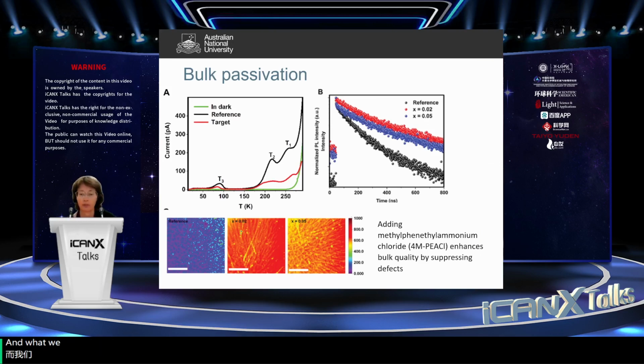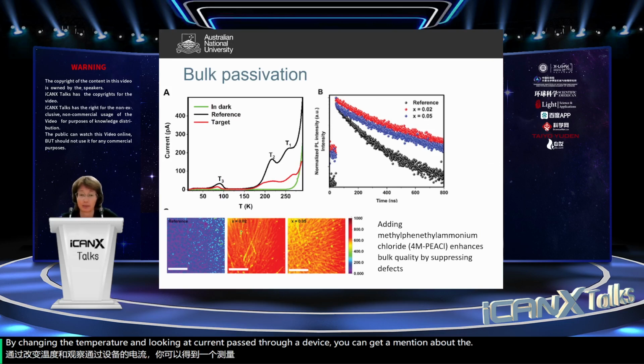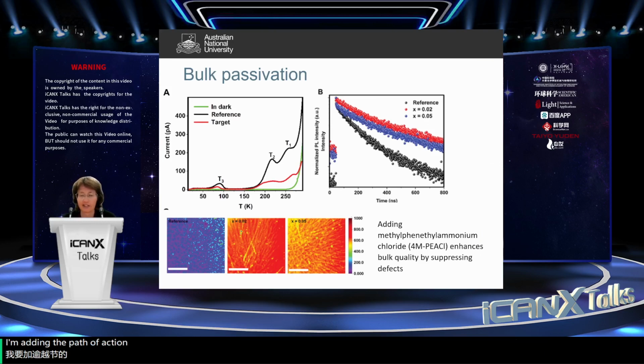And what we found is that adding methylphenethylammonium chloride actually enhanced the bulk quality by suppressing the defects. You can see these in these thermally induced current measurements. By changing the temperature and looking at the current passed through a device, you can get a measure of the number of traps. So adding the passivation material significantly decreased the number of traps.